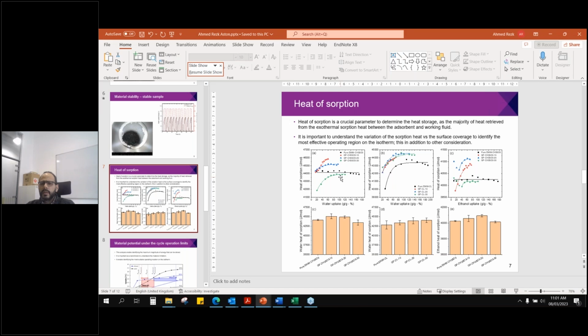It's a chemisorption effect, and the dispersion causes more active sites for the absorption. So we can find that the heat of sorption increases at higher concentration. So in some composites we can find proper trends, and when we look at the pure material itself without using the host matrix, some salts show constant heat of sorption. But again, we're going to use the solid composite in this application, this particular case study.